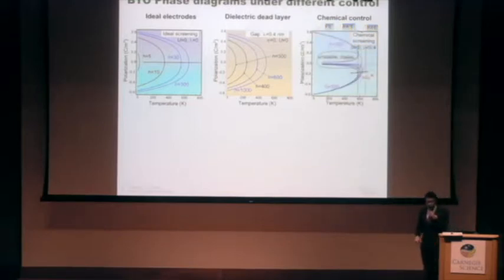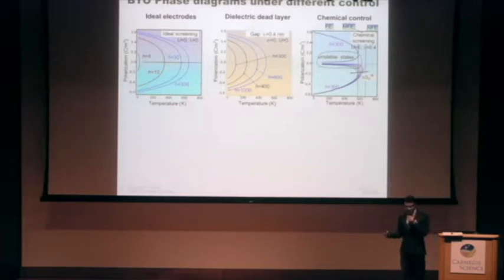Also, if you want to make sure that this is self-consistent, you can do this as a function of thickness, and what you find here is that for thinner films, your region of this mixed state is very large. As you go thicker and thicker, the surface becomes less important, and you find that the width of this mixed region is actually rather small. So this is kind of a sanity check almost.